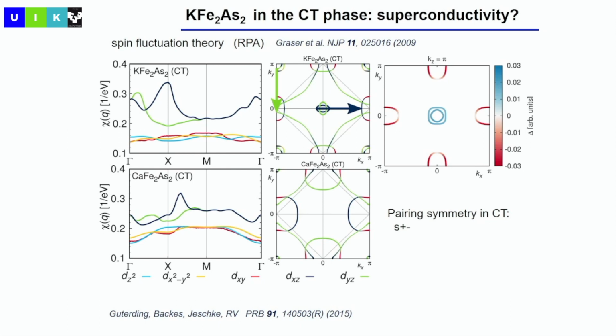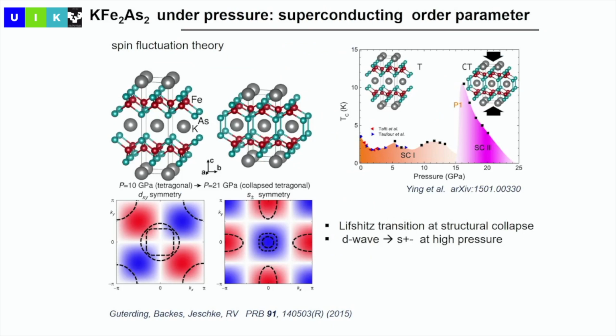nesting. So now one can calculate, with the formalism I was showing to you, the gap function, and therefore the order parameter. And what you obtain for this system is an S plus minus order parameter that you can see here with the color, the change between plus and minus contribution in the order parameter. Now, what is interesting, and probably this is my last slide, is that I was showing here the calculation for this region when we're in the collapsed phase. Now, if we do the calculation for this uncollapsed phase, and we do exactly the same